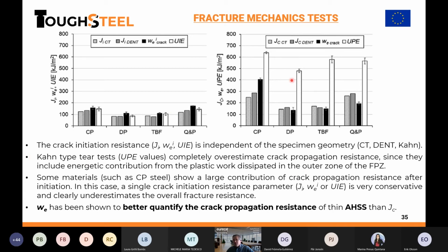In the Kahn tear test, we see that the results clearly overestimate the toughness compared to essential work of fracture, because again, there is a lot of energy contribution from plasticity. If you look at the comparison between the J-integral and the essential work of fracture, for some materials, some high-strength steels, it works pretty okay. But for some others, there is a noticeable difference.